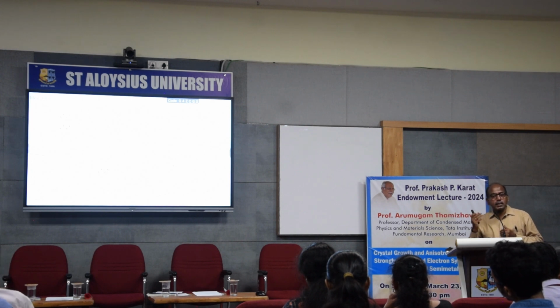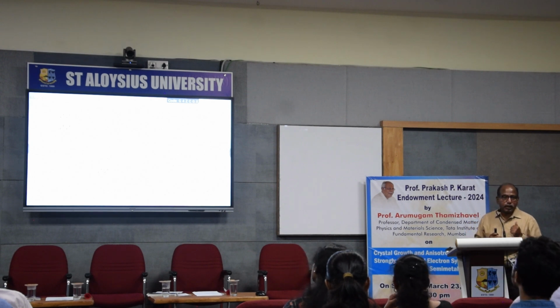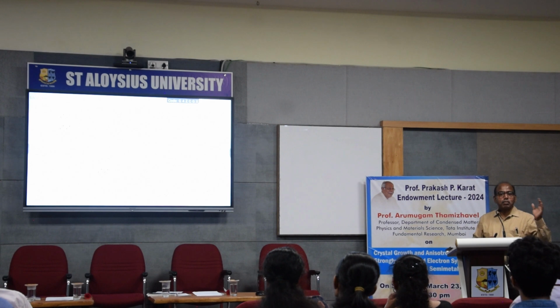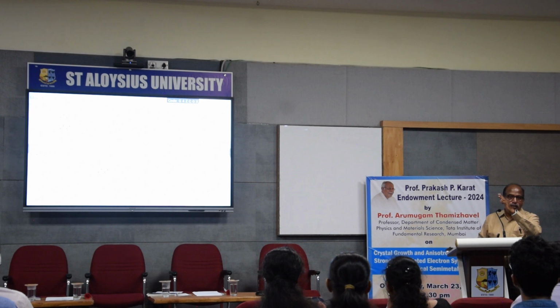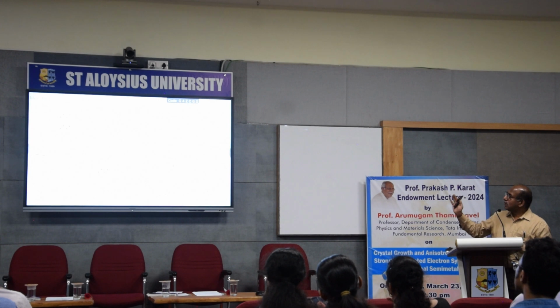Since I am interested in studying the magnetic properties of these materials, these single crystals are highly useful to find out the easy axis and hard axis of magnetization. Magnetic materials have an easy axis and a hard axis of magnetization. If you look at the chapter on ferromagnetism in Kittel, you can see that iron magnetizes relatively very fast, even by applying a small magnetic field, and then it saturates. That is the easy axis. Along the 111 direction, it may be a hard axis. Similarly, for whatever sample I prepare, I can find out the easy axis and hard axis directions